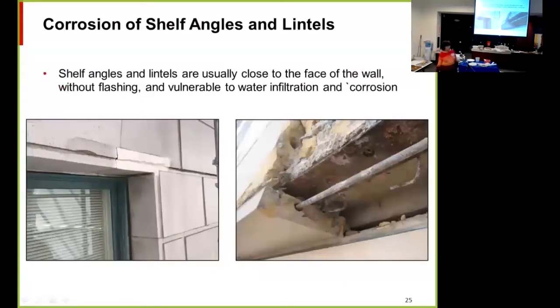Shelf angles and lintels, by their nature and their function, are really close to the outer surface of the wall. And that means that once water starts getting into the wall, they are the first things to corrode. And so they're really vulnerable to corrosion. And then when they start corroding, they'll crack the terracotta.